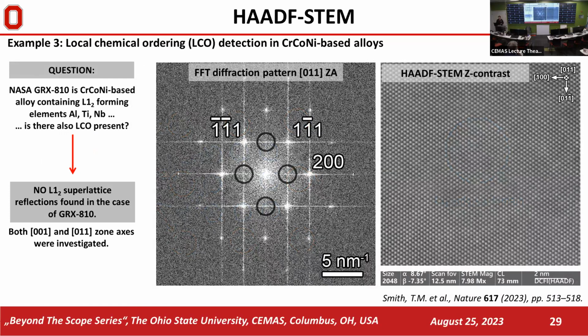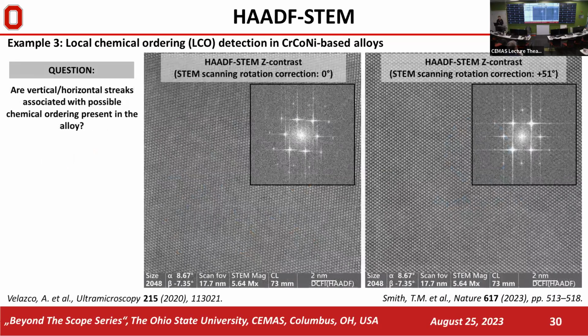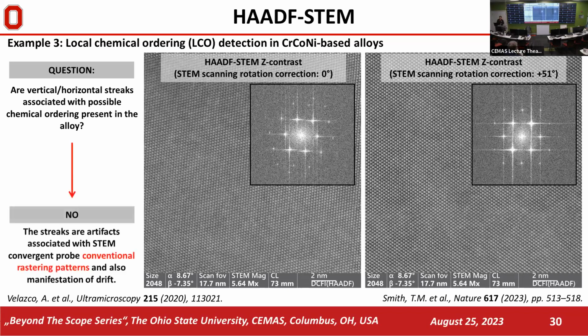There was another question which we got, and that was about vertical and horizontal streaks associated with that FFT diffraction pattern which we obtained from atomic resolution image, and we are pretty sure that this is not associated with chemical ordering present in the alloy, and